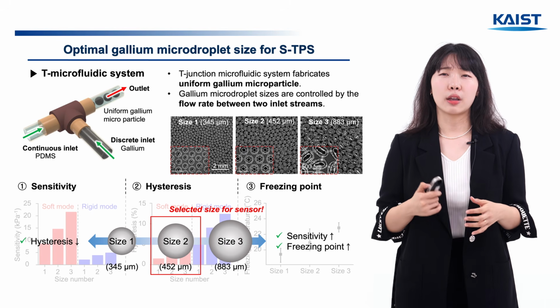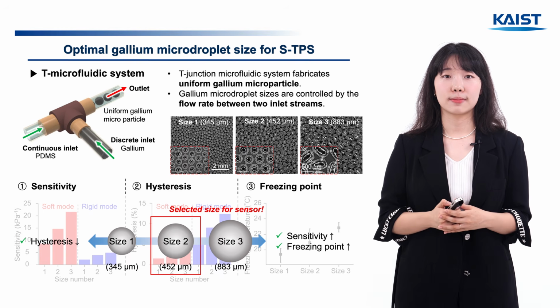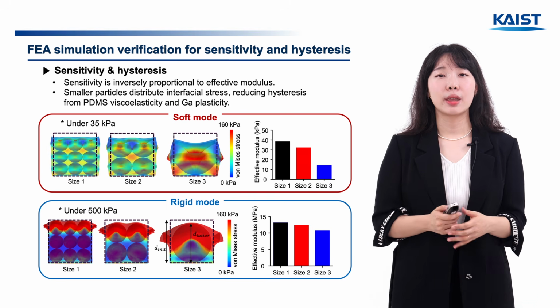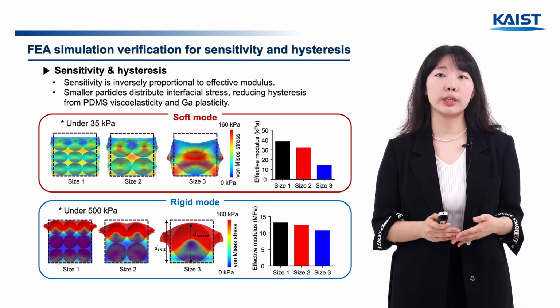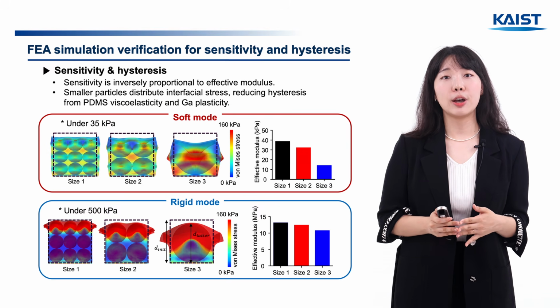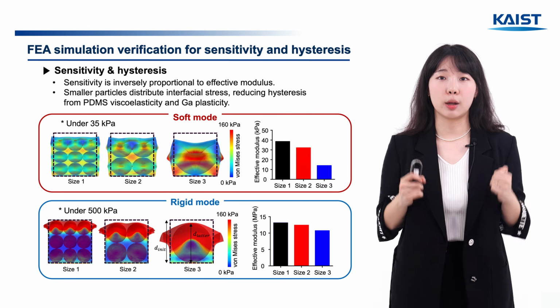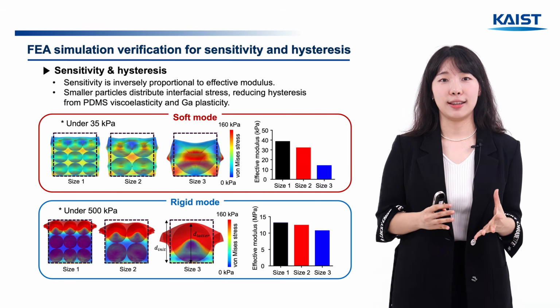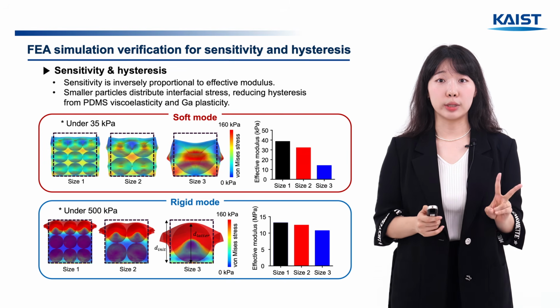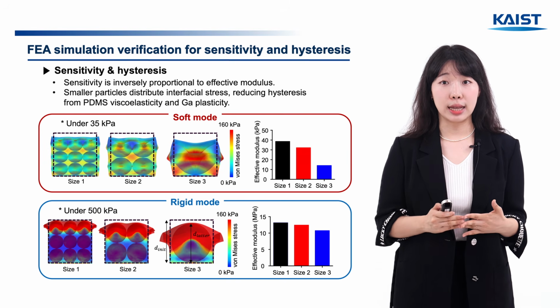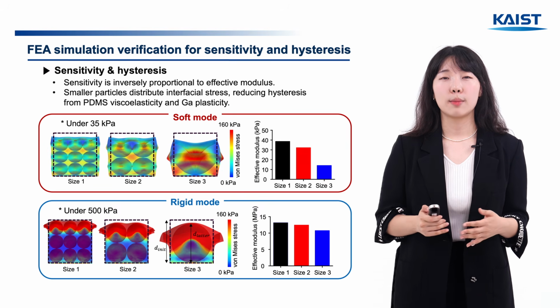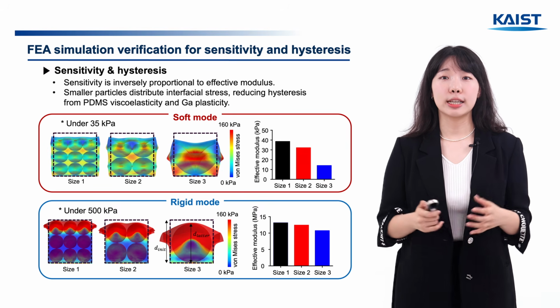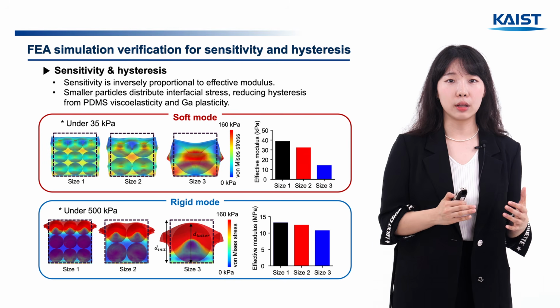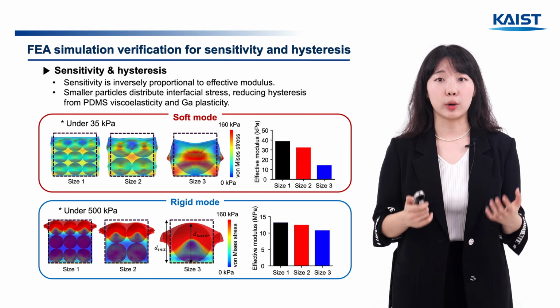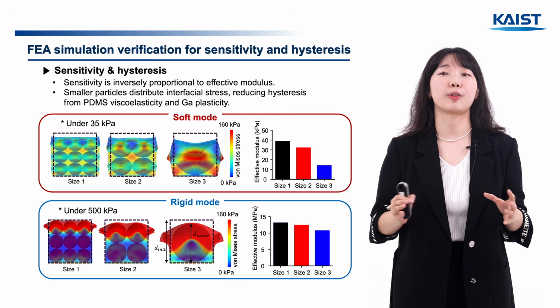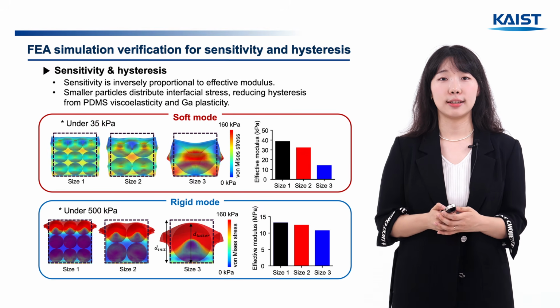And let me explain the cause behind each of these. Let's start with sensitivity. As I explained in the intro, smaller particles have higher internal pressure and a higher effective modulus, so they can resist compression, which lowers the sensitivity. Hysteresis comes from 2 sources, the viscoelasticity of PDMS and the plastic deformation of gallium, both driven by stress. The stress concentrates at the interface between the metal and the polymer. So the smaller particles, which have their interfaces more spread out, show lower hysteresis.